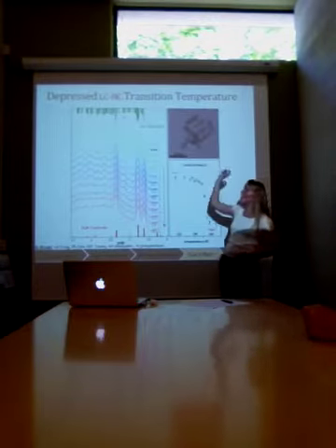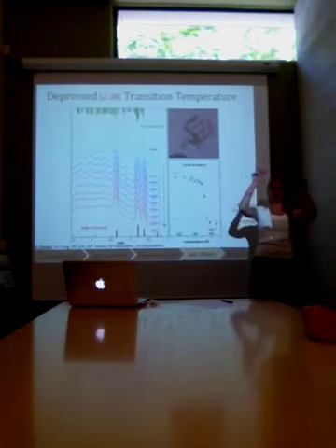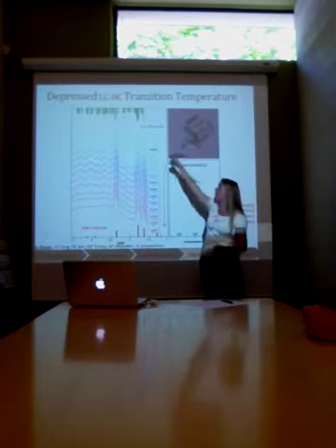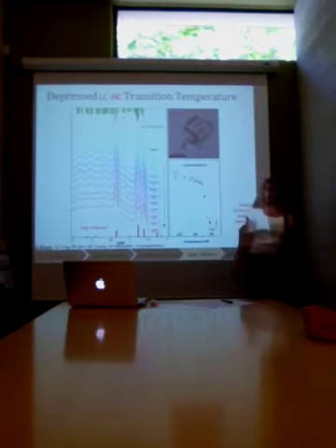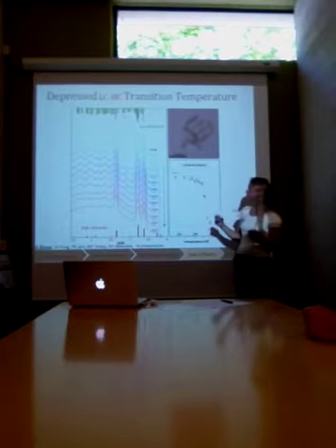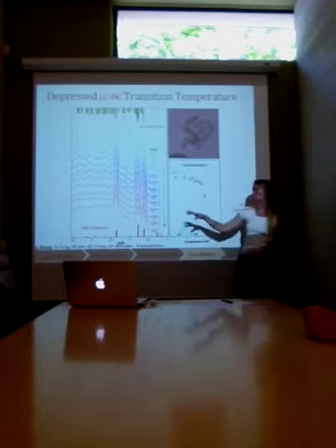For that, let's look to the structure and understand what the properties are in relation to the structure. The low chalcocite structure starts with a sulfur sublattice and has copper ions arranged in a very complex pattern around that sulfur sublattice. And that accounts for the very complex diffraction pattern. These vertical green lines at the top are the theoretical diffraction pattern from a perfect crystal. The high chalcocite phase shares some of these major peaks, but you can see it's a lot simpler.